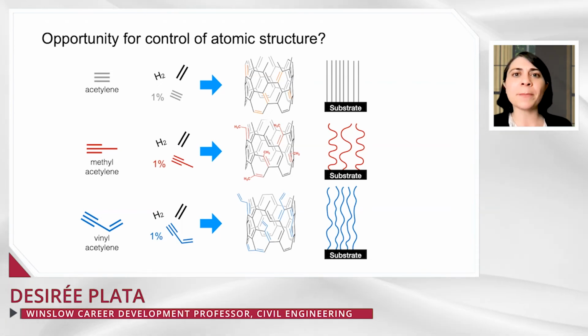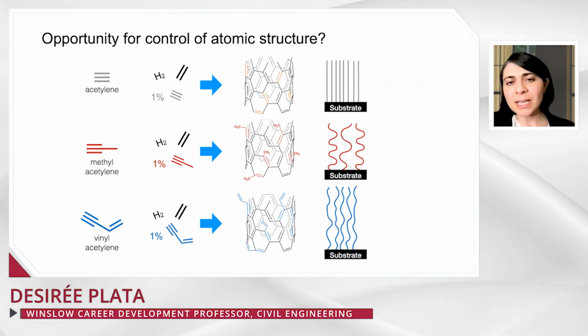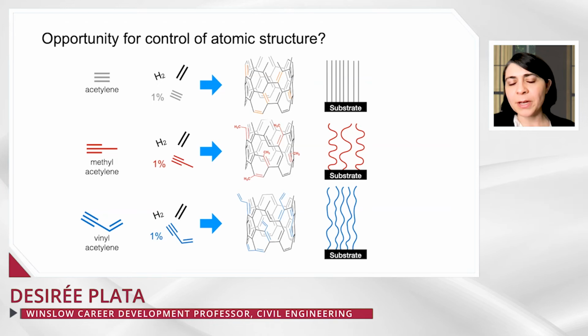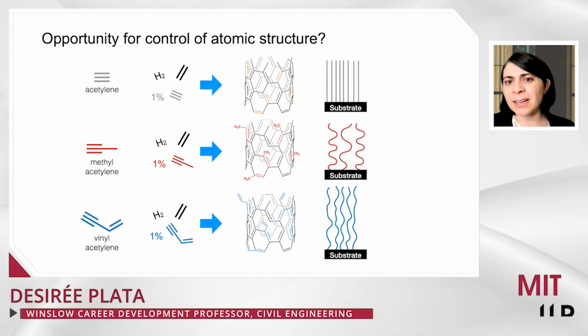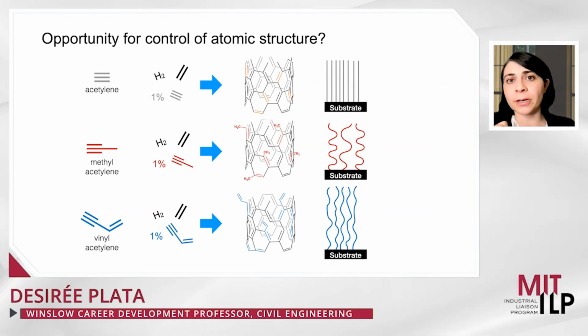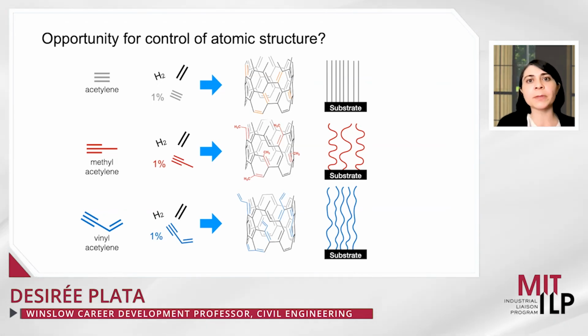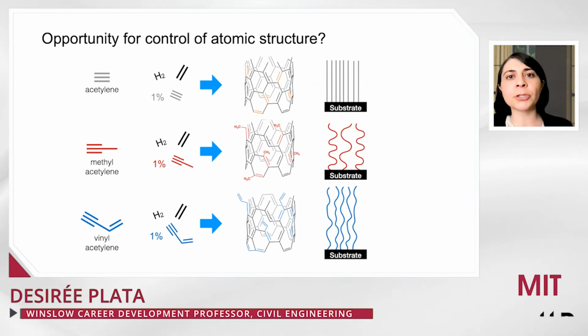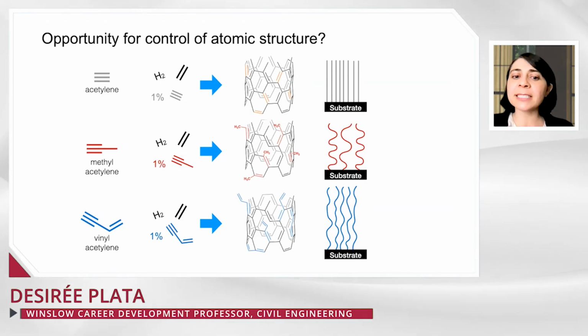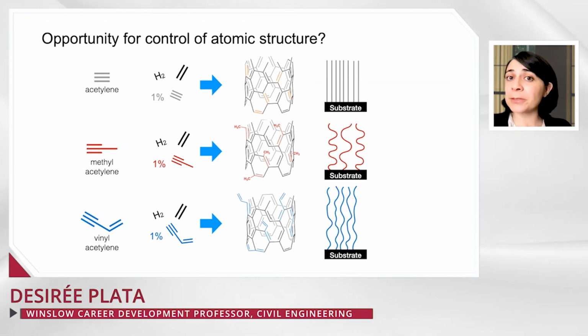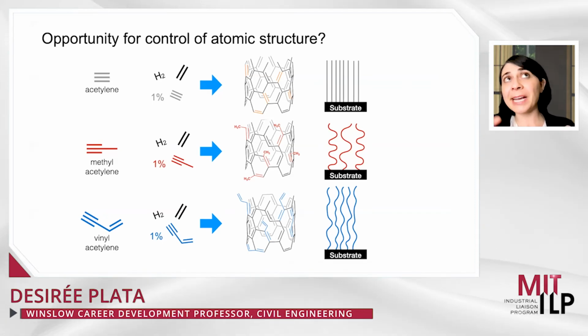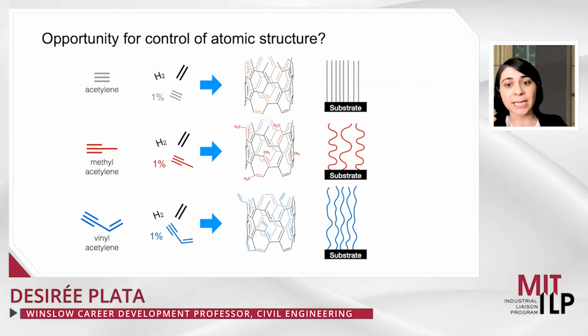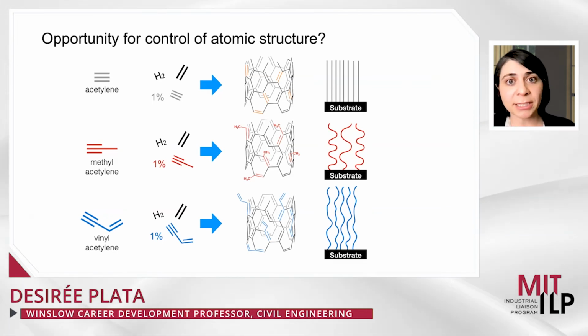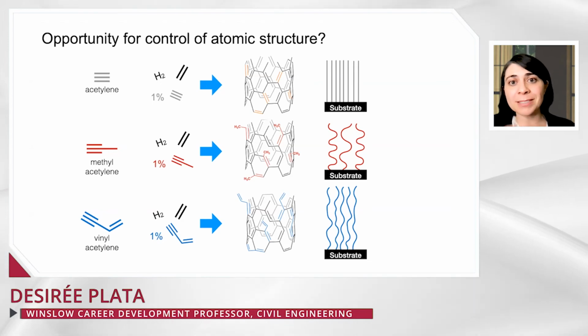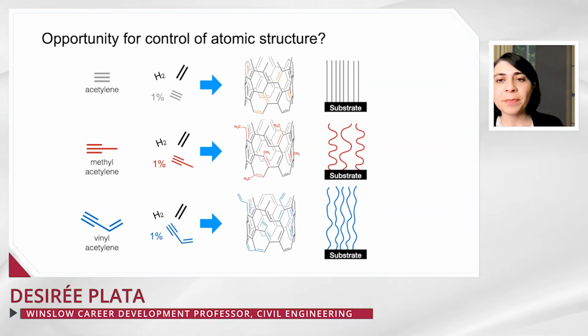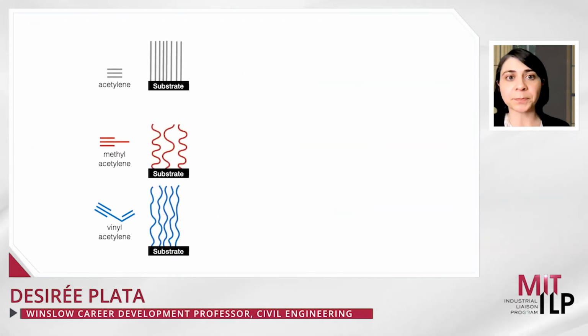We might hypothesize that methylacetylene, which has a CH3 group on the end that's sp3 bonded, might actually frustrate the ring closure and not be able to participate in a polymerization reaction. That might give a very tortuous structure. Vinyl acetylene, which has a filled pi orbital on the end, might actually be able to participate partially in these polymerization reactions and bond with those metal centers like on an iron catalyst. That might give a structure somewhere in between.